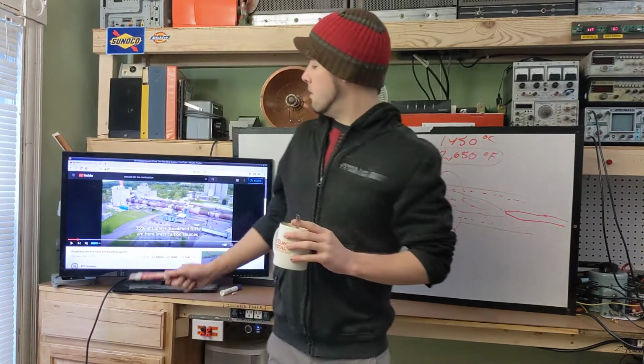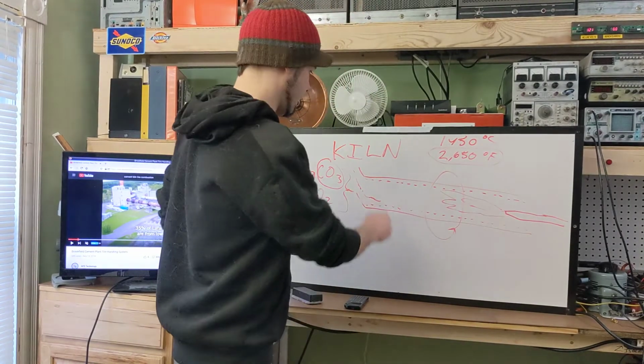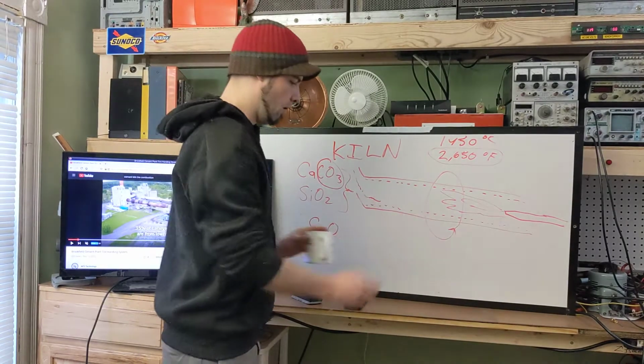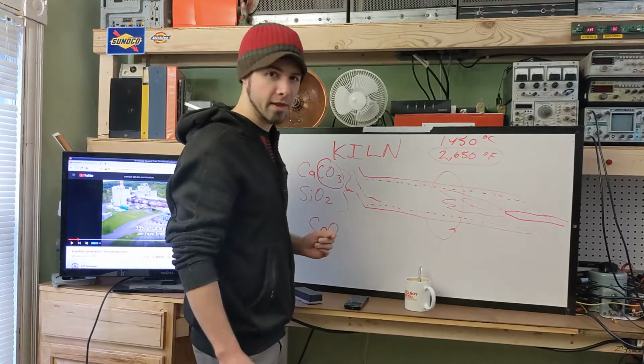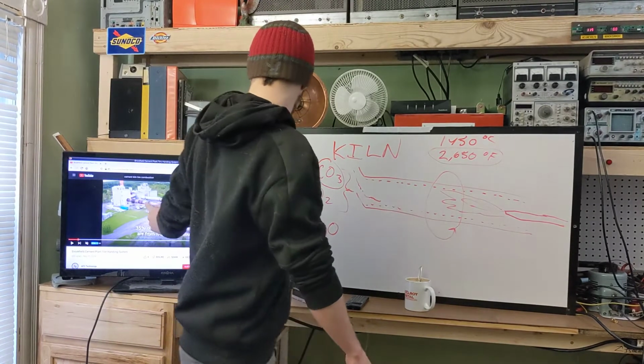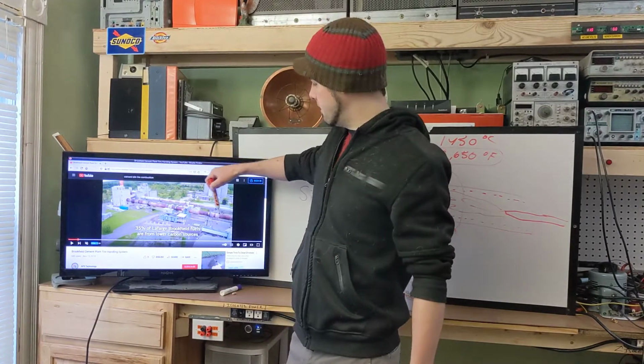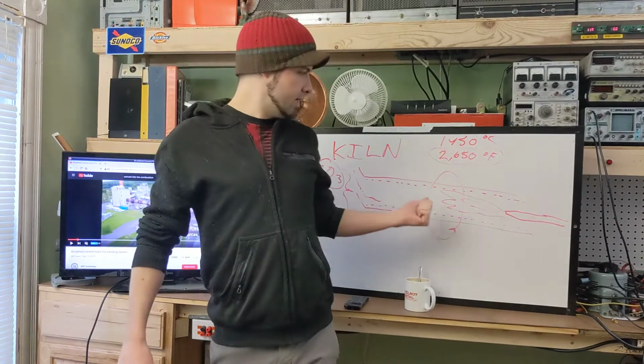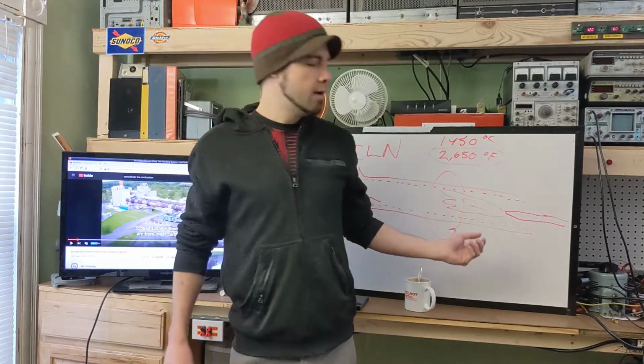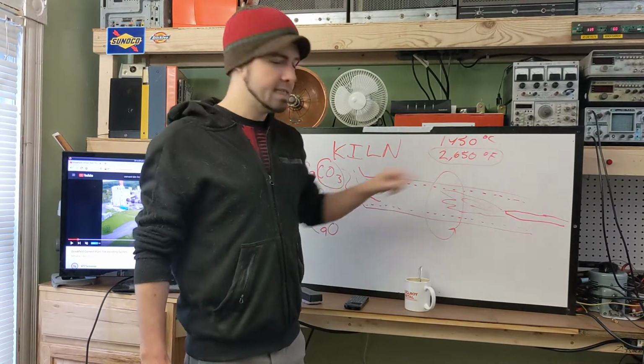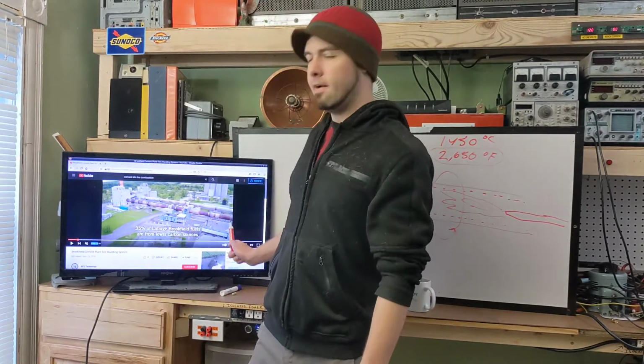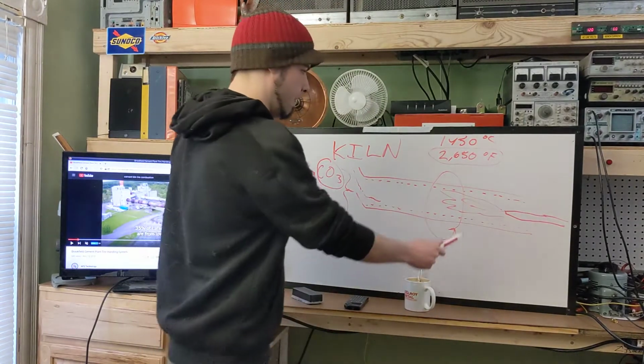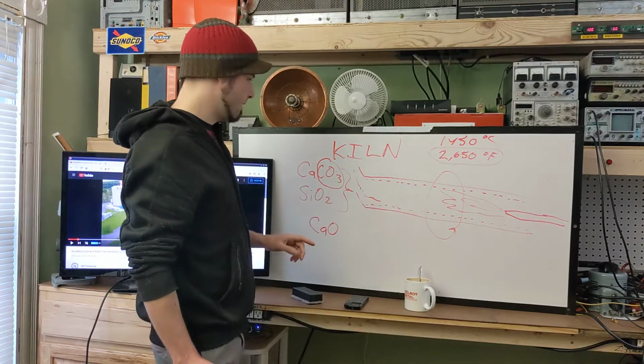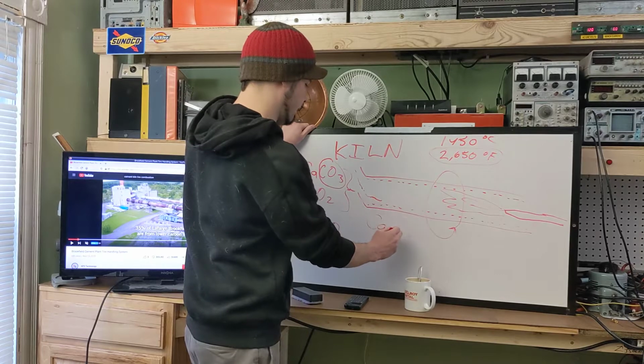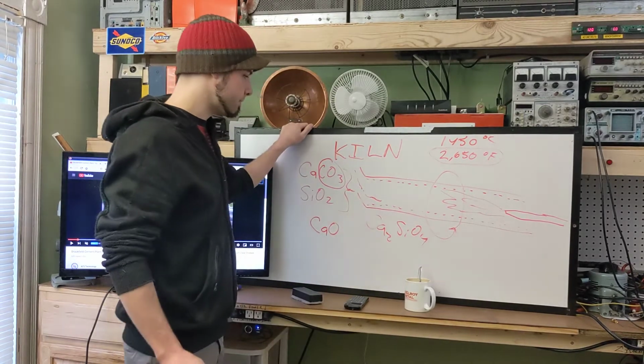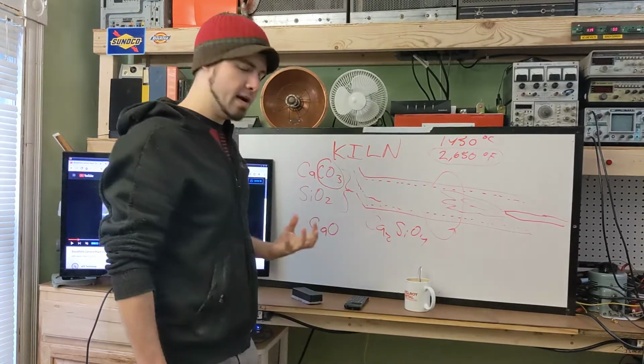Really, really hot. So that whole tube of this kiln is, like I said, lined with heat-resistant materials to, number one, keep the heat from melting the steel tube or burning through it, and also to keep the heat inside the kiln. We don't want a lot of heat escaping, because you can see there's a lot of surface area here exposed to the atmosphere. And even if the insulation is there, let's say they have a foot of refractory material lining the kiln, at 2,650 degrees Fahrenheit, over this large of a surface area, you're still going to have a lot of heat loss. So they got to fire enough coal into this kiln to run the process of creating cement, calcium silicate, and all its various formats, and also sintering the material and creating what's called clinker.